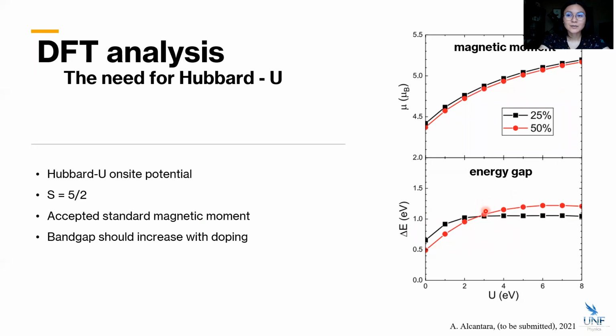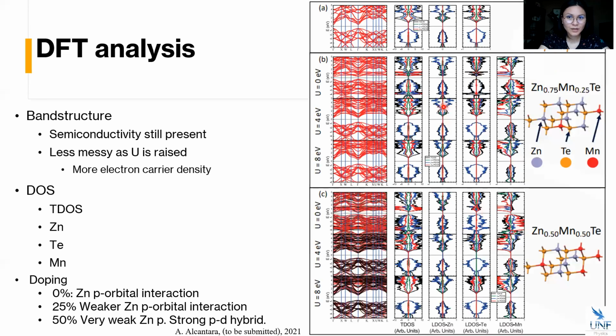So now we can look at the system under the proper analysis. So this huge figure is the evolution of the zinc telluride doped with 25% and 50%. And this is also for the Hubbard U values of 0, 4, and 8 to compare. As I originally said, the zinc telluride was just a P interaction. But if we come down here and we look at the high magnetization for U is 8 at the manganese, we can see that the manganese is now starting to provide more interaction in the D orbitals for the tellurium, and zinc is essentially reducing from the system.